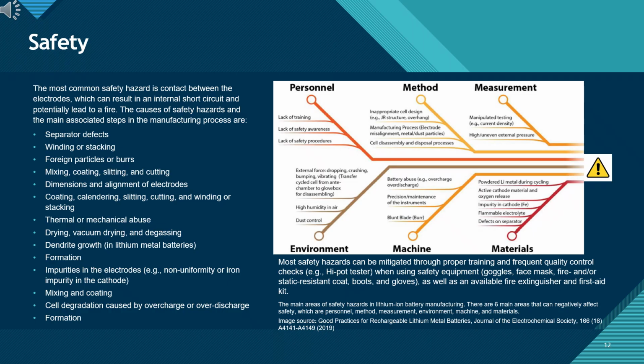Safety. Safety is one of the most critical aspects of lithium-ion battery manufacturing because many process steps can unintentionally create conditions that lead to internal short circuits, thermal runaway, or fire. The single most common hazard is direct contact between the electrodes, typically caused by defects in the separator, misalignment during winding or stacking, or the presence of burrs and foreign particles introduced during mixing, coating, slitting, or cutting operations.